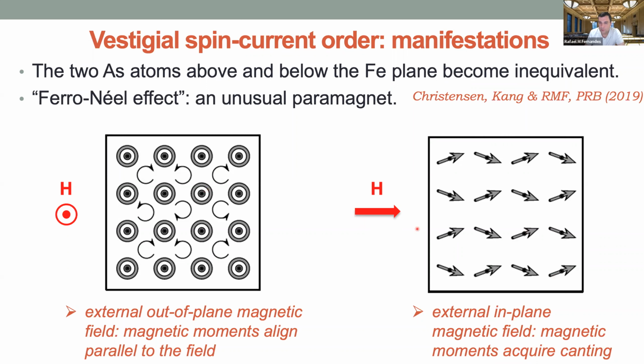But here is actually pretty bizarre. If I apply a field in-plane and I have these spin currents, I not only get a component of the spins pointing parallel to H, but I get a component that is perpendicular and staggered. So a magnetic field here induces both ferro and antiferro orders, if you wish, and you get a canted phase. This would be direct evidence that the spin current phase exists.